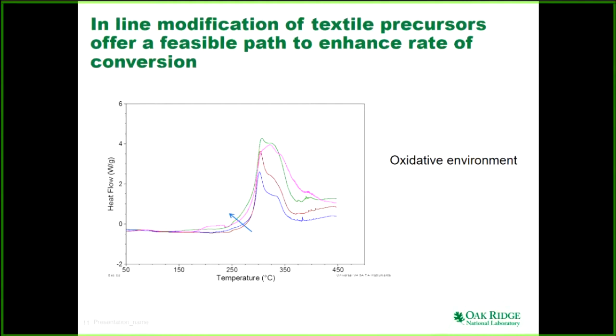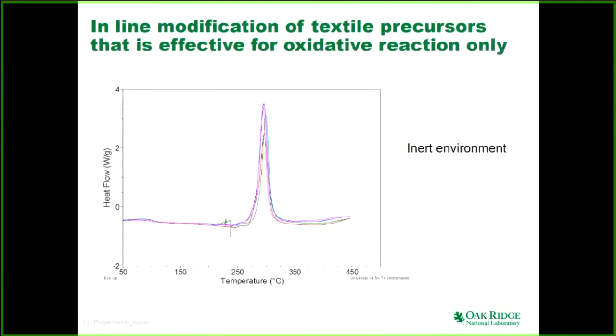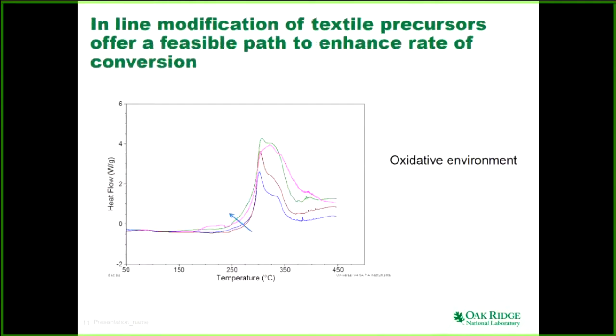It is oxidation. How do we know that? So we ran the same materials in nitrogen, in inert atmosphere, and you see in inert atmosphere only the heat affects, and it is not much. You can see that the peak is almost at 300 degrees Celsius, so the peak is shifted. So it's not necessarily the heat. Air and heat both are working there. So it is an oxidation reaction, and that does this pre-stabilization, which will accelerate further and perhaps will increase the throughput of carbon fiber manufacturing.